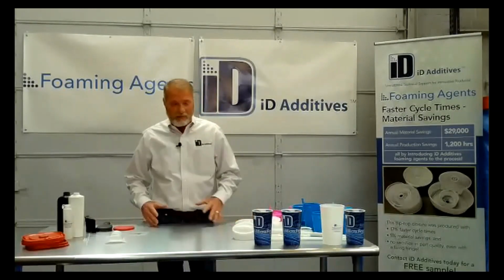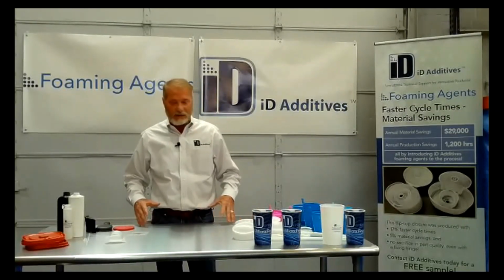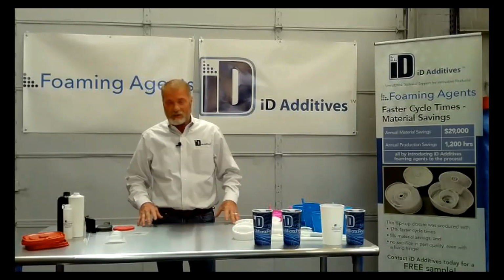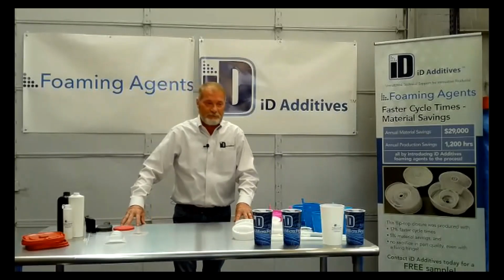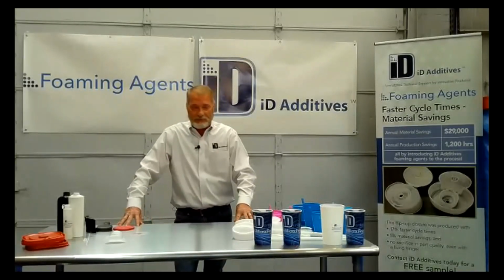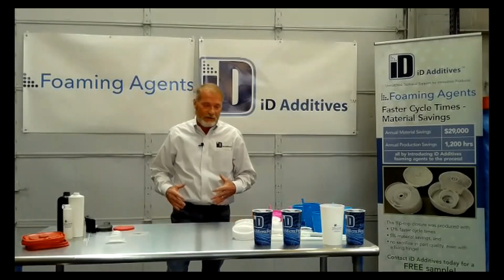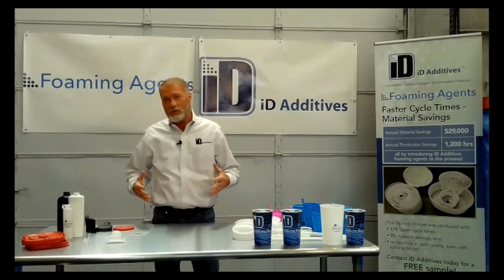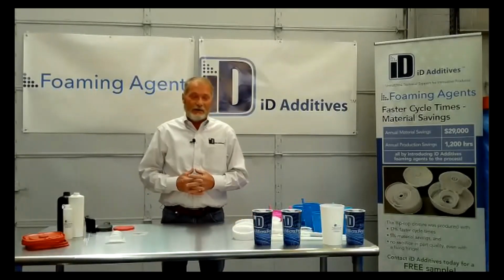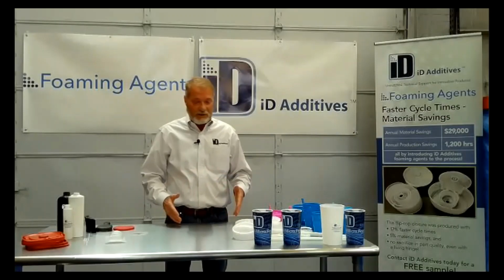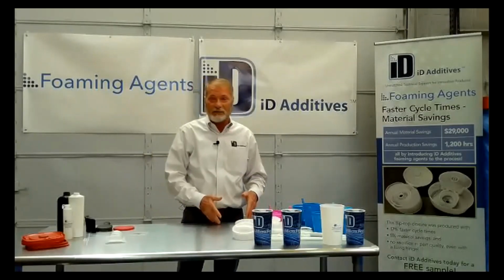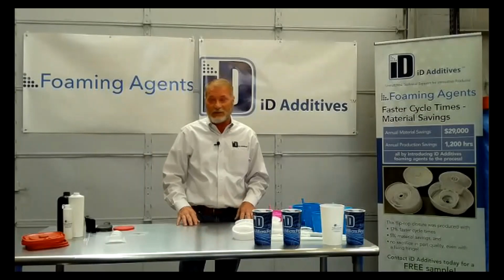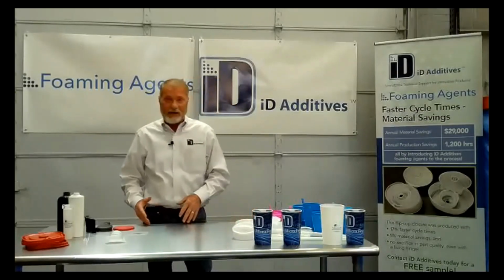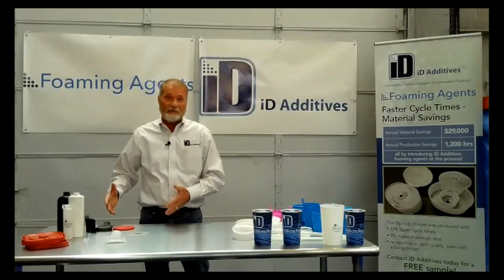So there's different applications. One thing stands true about all these applications is temperatures. Controlling the temperature gives you a consistent shot to shot. And what I mean by temperatures is foaming agent, it takes heat for foam to go off. And most of our products, until we get into our engineered grade for polycarbonate, nylon and those kind of applications, that product kicks off about 450 F.